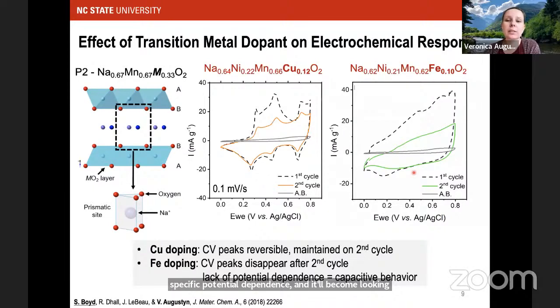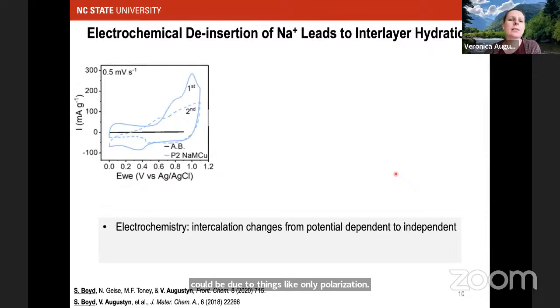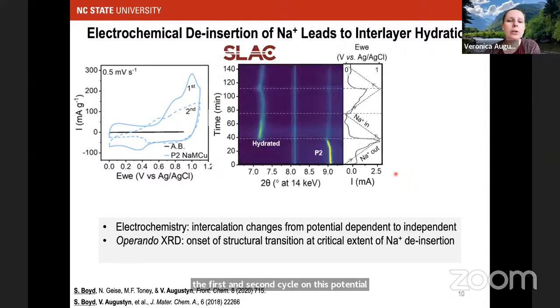So an ideal capacitor in a cyclic voltammogram will look like a rectangle. This is not a perfect rectangle, it's tilted, but that could be due to things like ohmic polarization. So what's happening mechanistically in these materials? It turns out that the differences that we see between the first and second cycle are really due to a very significant structural transition, an irreversible transition that takes place in the first cycle, where you take sodium ions out. If you take too much out, then very quickly you have a structural transition.